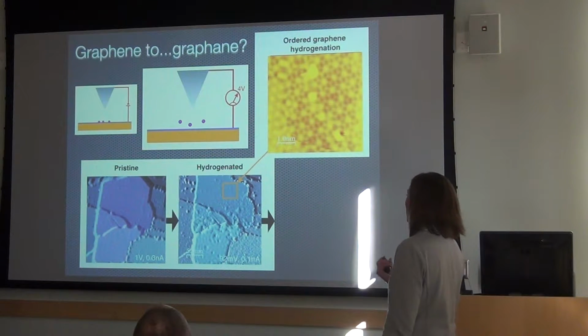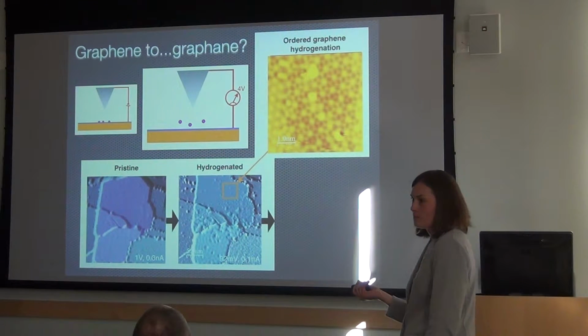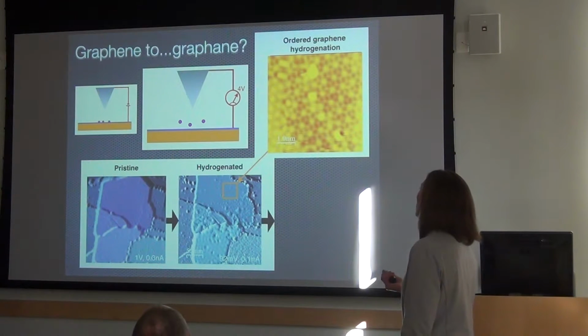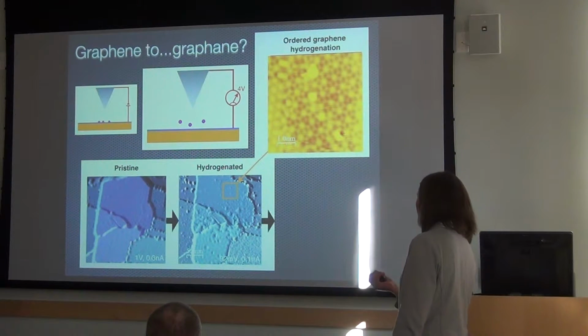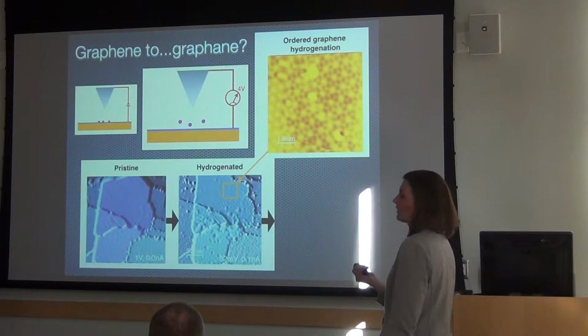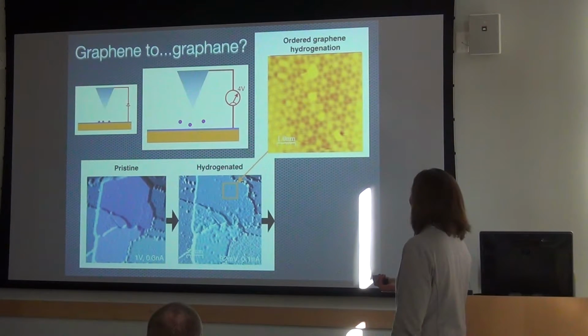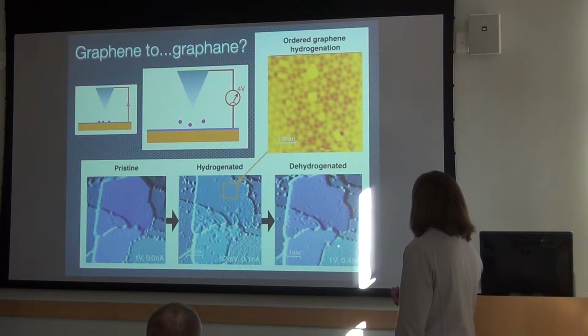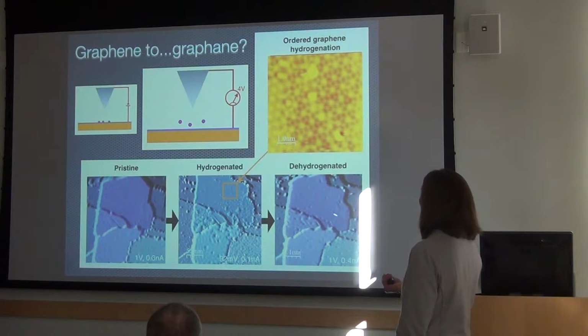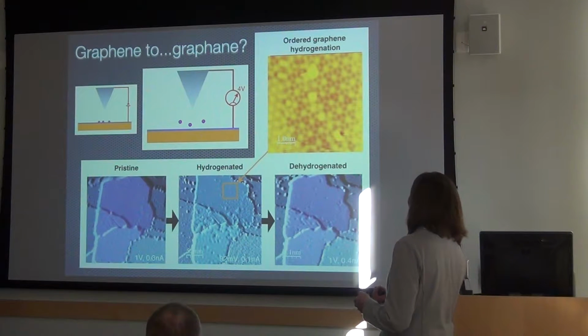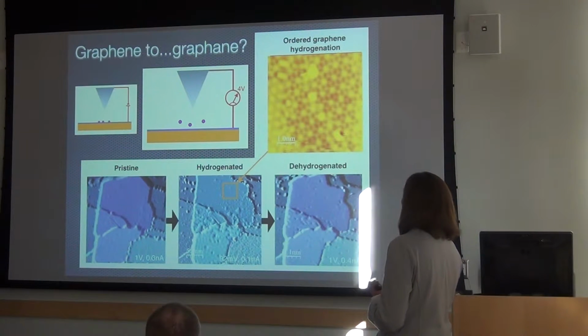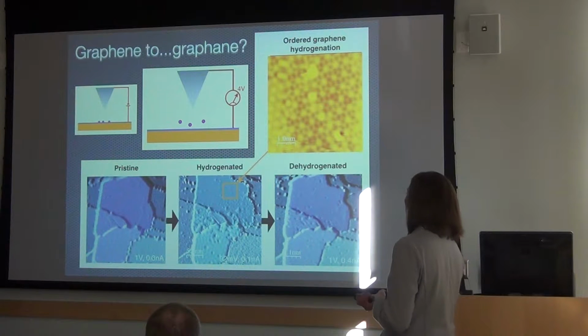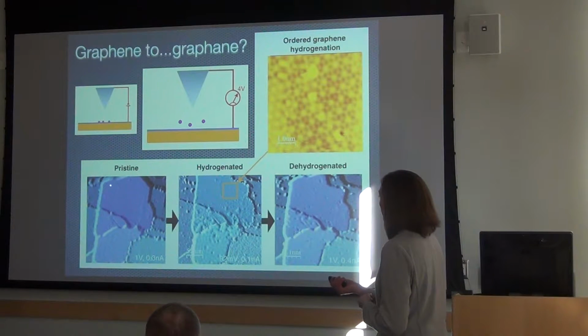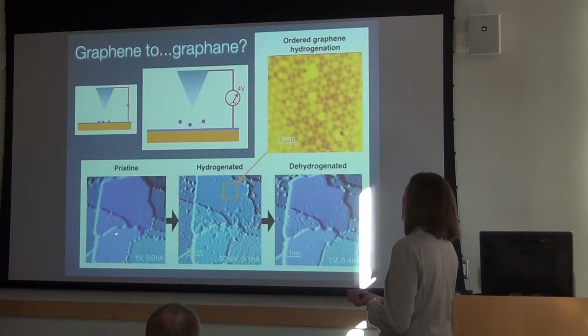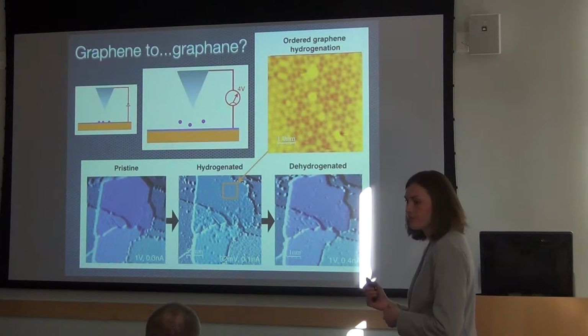Okay, and this process is also reversible. If we image at a relatively high bias, around 4 volts, we're able to remove the hydrogen layer. This is an example of that, and there's some damage on the sample here from various other experiments that we were trying, but you can tell that the lattice has returned because you can see a moire pattern in the pristine island that's the same as in this dehydrogenated island.